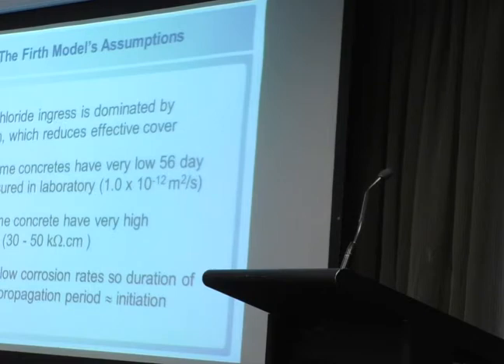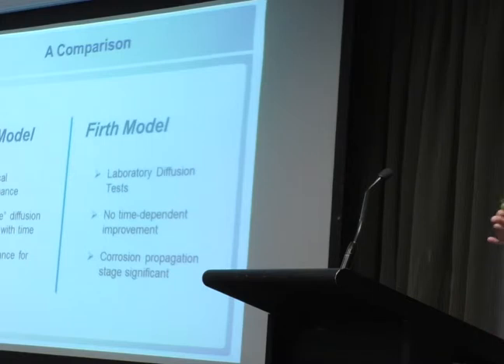And even though silica fume concretes have very low 56-day diffusion coefficients, because they're measured on fully saturated concrete, they're still significantly higher than what you would typically observe in the field. It said that you need to take advantage of the fact that silica fume concretes have very high resistivities, and consequently, your propagation period was important. And so if you just look at those two models, you can see how potentially confusing that would be to a would-be specifier trying to look at solutions produced with each of them.